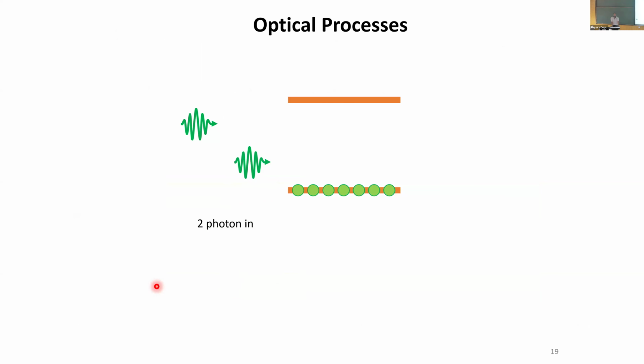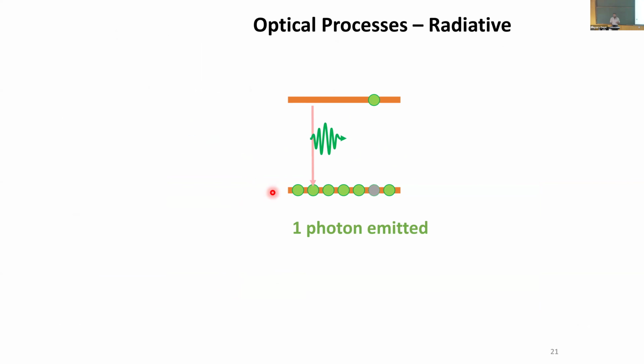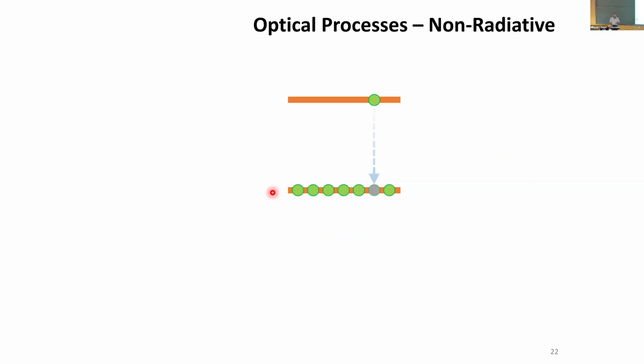If you go to a basic semiconductor, let us say you have your basic valence band and conduction band, and you come in with two photons, and these two photons can excite two electron hole pairs. They do nothing, these electron hole pairs should relax. And that relaxation can again happen in two ways. One of the ways is you come down, you emit a photon, so you give back the energy. And the other way is you do come down, but you basically emit heat. So this is phonon assisted. So we make use of this heat part. So I am explicitly relying on heat being generated upon absorption. Okay, so take note of this point.